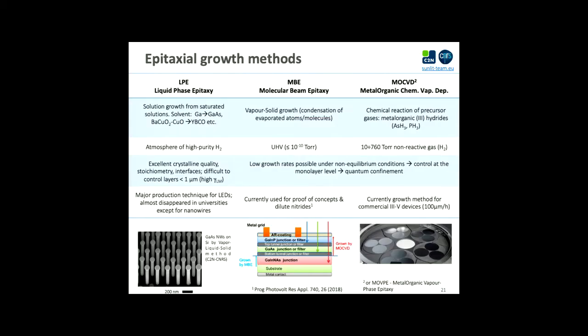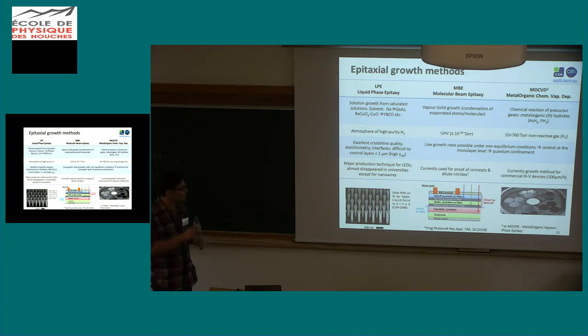So here, just one slide on the epitaxial growth methods we use for III-V materials. At the beginning, as I already mentioned, a lot of devices were made by liquid phase epitaxy. This is a solution-based epitaxial growth of crystals. The solution in this case is a melted metal, for example for gallium arsenide it would be melted gallium. It's performed at atmospheric pressure with some high purity hydrogen, and it gives you really excellent crystalline quality, stoichiometry, and interfaces.